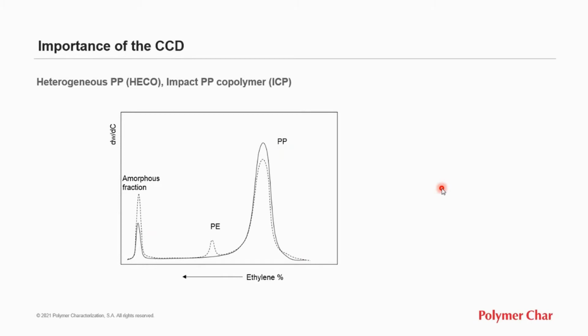For polypropylene and ethylene propylene copolymers, the CCD is related to irregularities in the chains, which also reduce the crystallinity and reduce the temperature. For example, incorporation of ethylene as comonomer, but also the tacticity or regio errors. Here we see a typical distribution of a heterogeneous impact copolymer with a peak at high temperature due to the most crystalline isotactic polypropylene. Then some crystalline propylene-rich EP copolymer, even some pure polyethylene peak we can obtain sometimes, and then an amorphous fraction, with a higher level of ethylene, EP rubber, observed at room temperature. So differences among products can be clearly discriminated by the chemical composition distribution, while the molar mass distribution has little information. There are very small variations in the molar mass distribution.